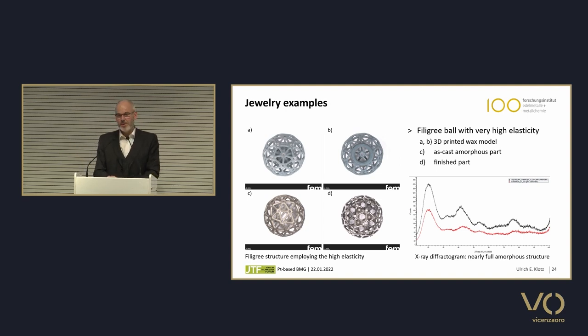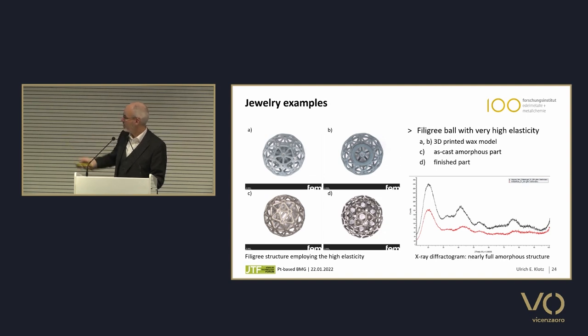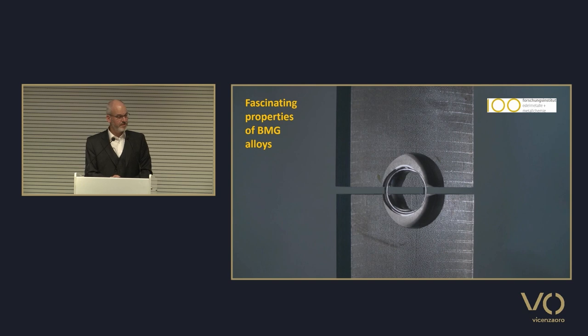And this part was indeed amorphous. We proved this by X-ray diffraction. The X-ray diffraction pattern of a crystalline material usually shows sharp peaks. If these sharp peaks are missing, this is an indication of the amorphous state. And this is the case here. There is no sharp peak here. There's this broad peak. So that was a nice example.